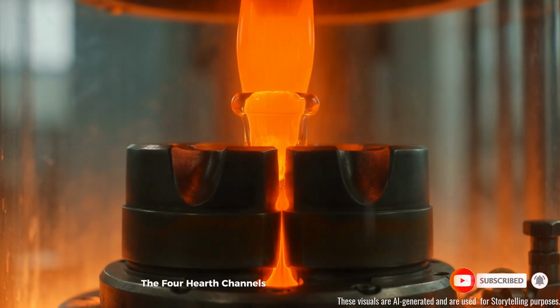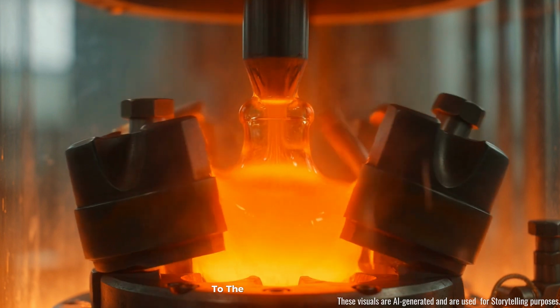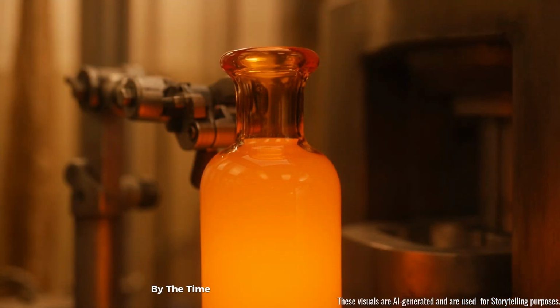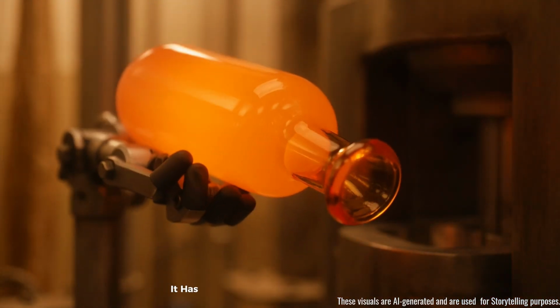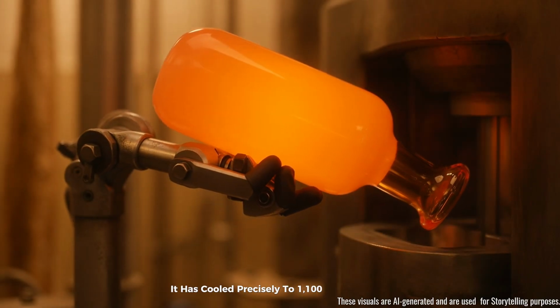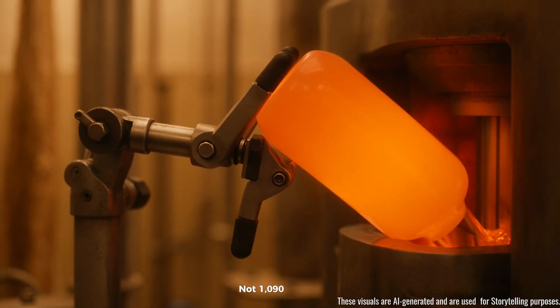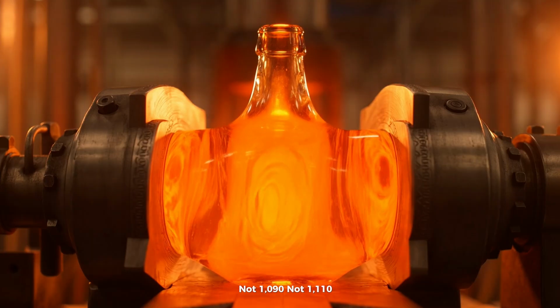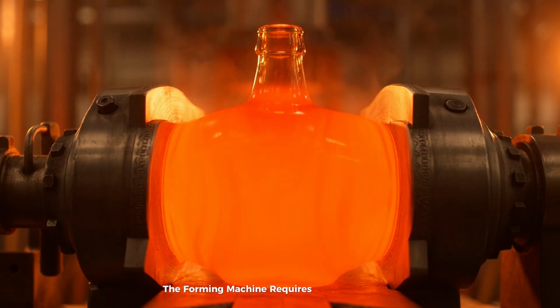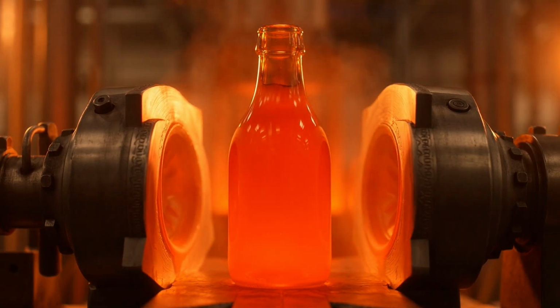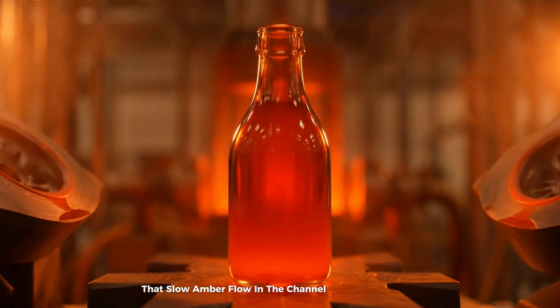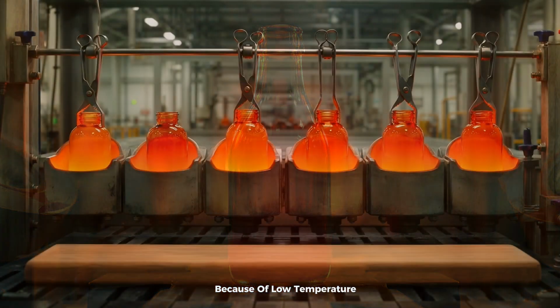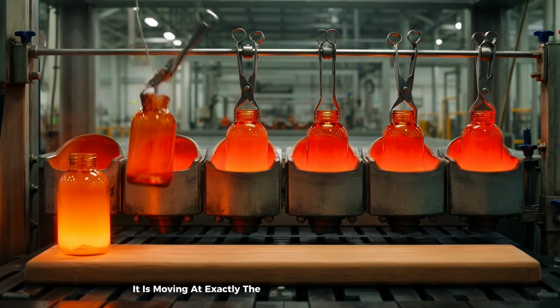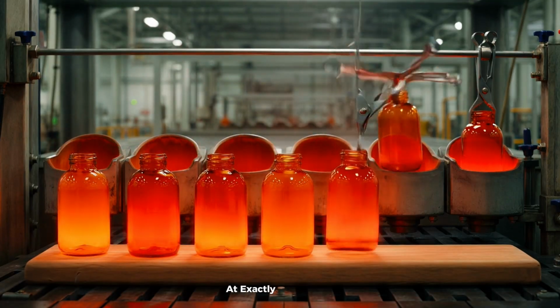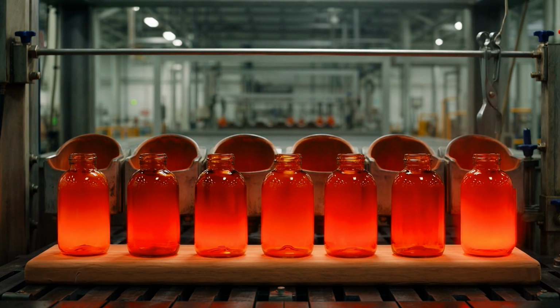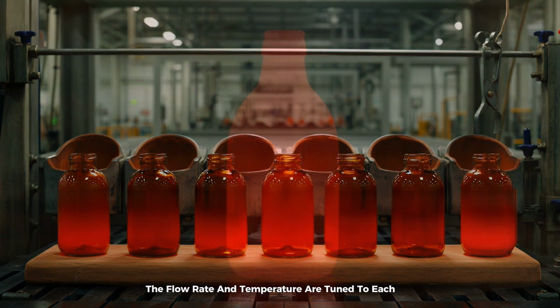The 4 hearth channels carry the molten glass from the furnace to the 4 forming machines. By the time the glass reaches the end of the channel, it has cooled precisely to 1,100 degrees Celsius. Not 1,090, not 1,110. The forming machine requires a specific viscosity. That slow amber flow in the channel is not moving slowly because of low temperature. It is moving at exactly the right speed to arrive at the feeder at exactly 1,100 degrees. The flow rate and temperature are tuned to each other.